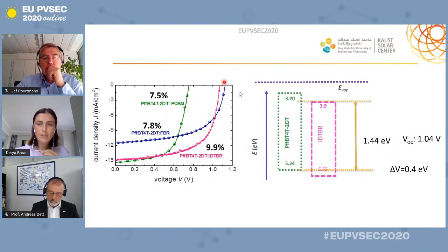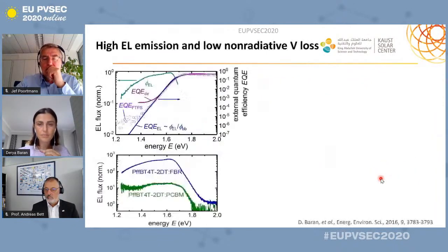So with this particular blend, this gap of 1.44 was accompanied by a 1.04 voltage, which brings this voltage loss to around 0.4 eV. And the main reason for this was obviously in the radiative recombination, because we quickly realized that the non-fullerene acceptors in combination with the polymer donors are able to have a much higher order of radiative recombination compared to the fullerene ones, which was quite exciting.